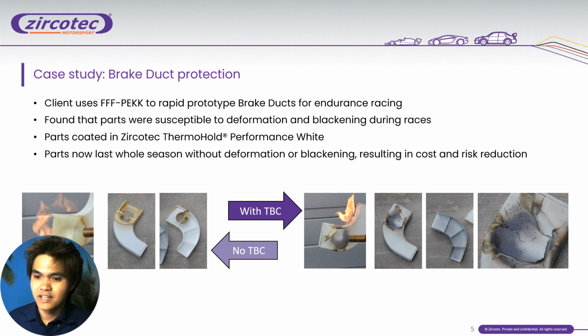Our next test is the flammability test for a brake duct. They used a plastic 3D printed brake duct and a simple flammability test, which shows that without the thermal barrier coating, the fire would easily pierce a hole through the plastic part, but with the coating, it was not able to create a hole in the plastic.